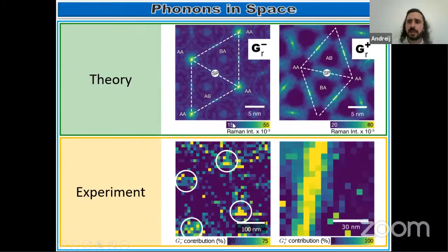And for the GR plus mode, both the theory and experiment say that we have large intensities at the SP solitons. Okay, so both the theory and experiment are in agreement, and they elaborate that these new peaks that we observe and measure modulate over the space. So they have different intensities across the space. So this gives rise to a new concept, which is phonon localization.